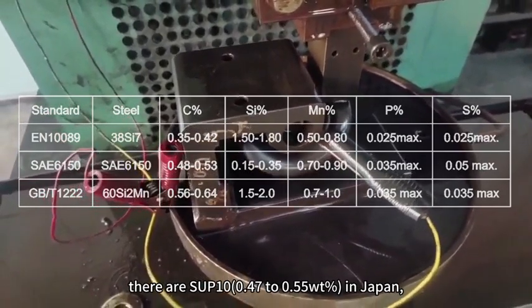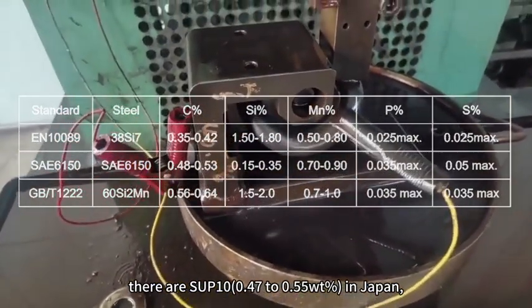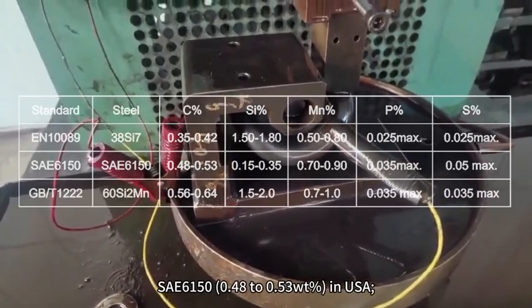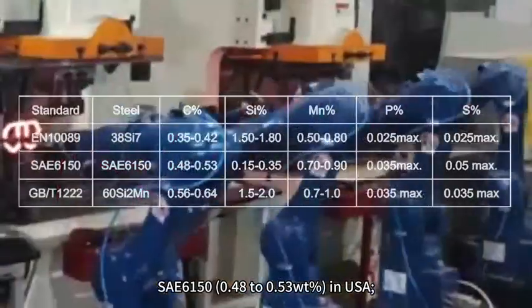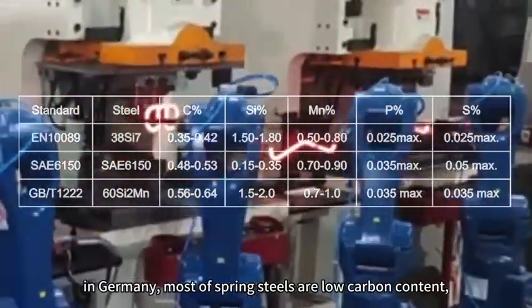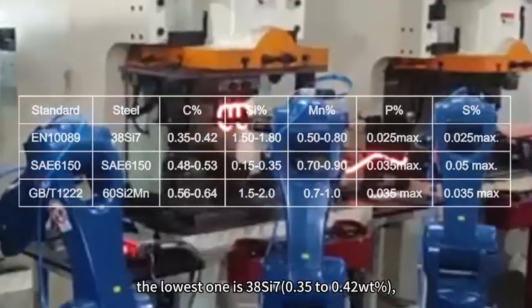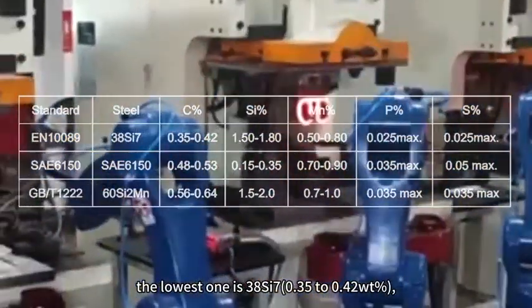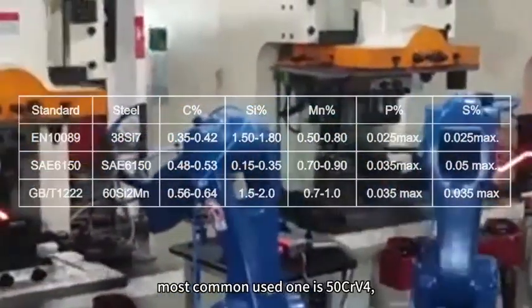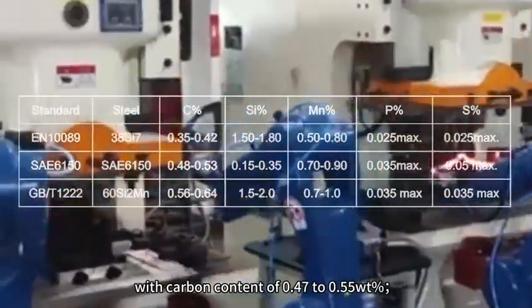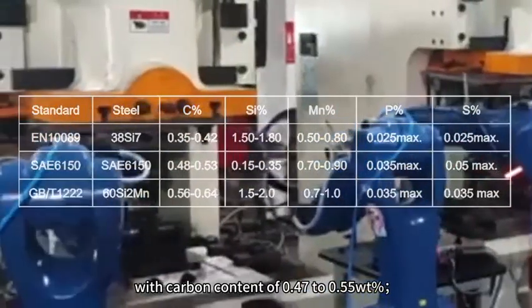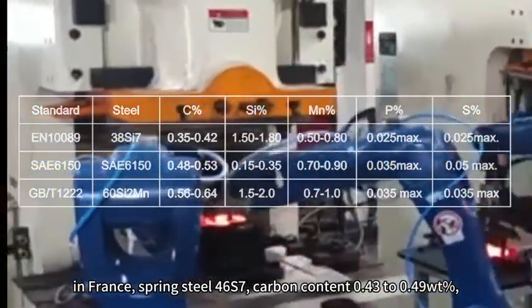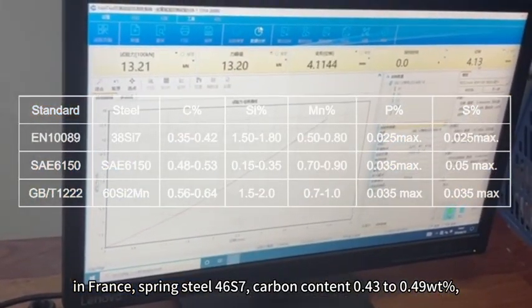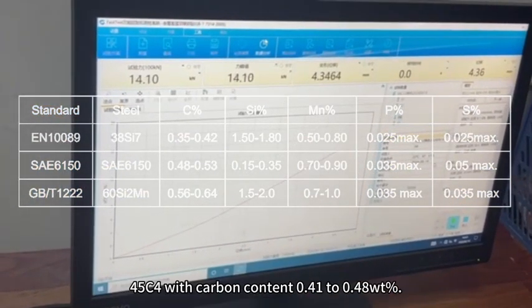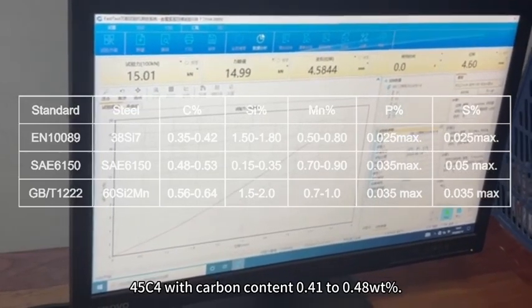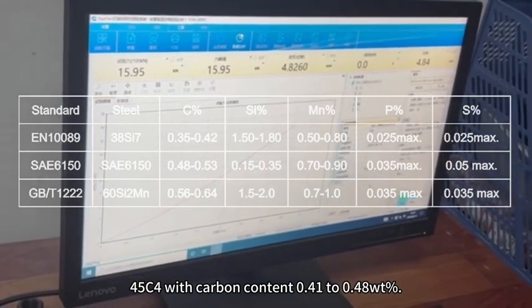There is SUP10 in Japan, 0.47 to 0.55 Wt%, and SAE6150 in the USA, 0.48 to 0.53 Wt%. In Germany, most spring steels are low carbon content. The lowest one is 38Si7, 0.35 to 0.42 Wt%. The most commonly used one is 50CrV4, with carbon content of 0.47 to 0.55 Wt%. In France, spring steel 46S7 has carbon content of 0.43 to 0.49 Wt%, and 45C4 has carbon content of 0.41 to 0.48 Wt%.